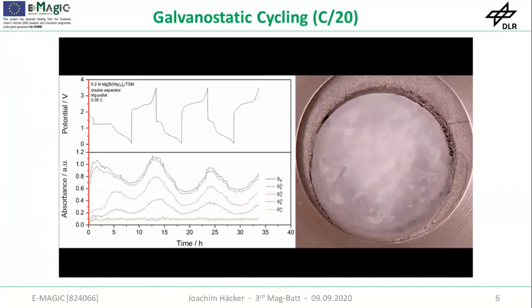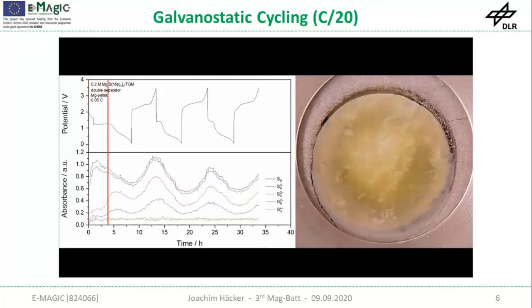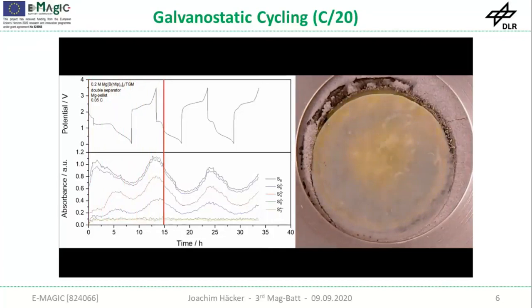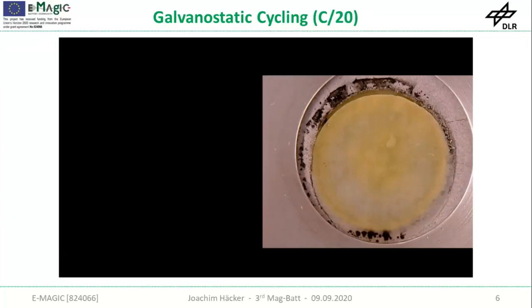Here you can see the voltage profile in the top part of a magnesium-sulfur cell cycled at C/20, in the bottom part the corresponding response from the UV spectra, and on the right side the operando microscopy picture. You might see now during discharge there is a coloration of the separator, and towards the end of the discharge it vanishes, starts to color again, and then is decolored again completely. You can also see a black coloration around the magnesium ring at the edge, which might be electrolyte decomposition or some sulfur precipitation, polysulfide forming magnesium sulfide at the anode surface.